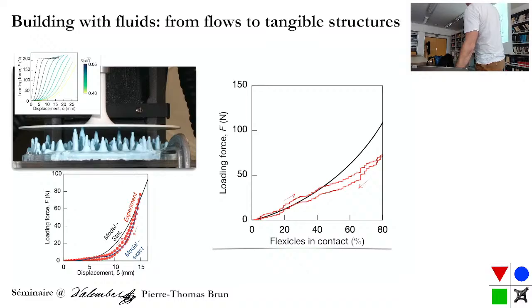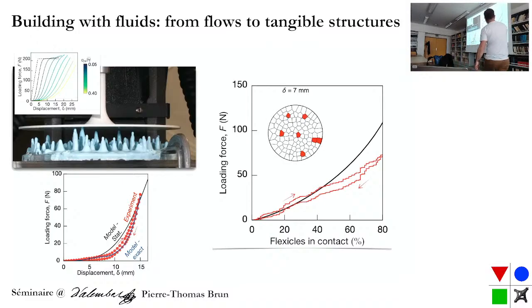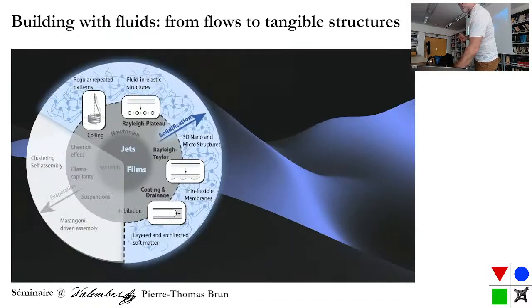And so you can plot the force as the number of contacts. So these are my hairs, and as they appear red, they're in contact with the plate. So the force is now increasing with the number of contacts. And what's interesting, at least for us and for reviewer 3, is that the force can be actually predicted by just counting how many of those hairs are in contact. Because I know their size, I know their distribution. So if I can count how many are in contact, I can tell you what the force is. So it's a minimal force sensor, so we say.